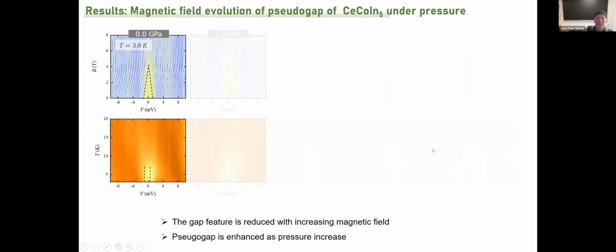How about magnetic field? So for comparison, I put those two, the magnetic field dependence and the temperature dependence. Here, for the magnetic field dependence, the temperature is 3.0 Kelvin. As you can see, unlike the temperature dependence, where the size of the gap is pretty much constant, in the magnetic field dependence the size of the gap actually is suppressed, like this one. And this is data at 3.0 Kelvin.